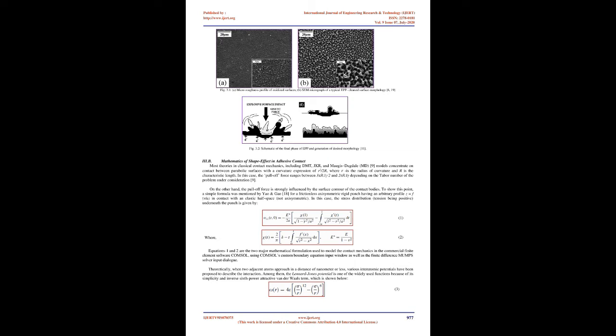2 general models of the contact behavior have been proposed: 1. The Derjaguin-Muller-Toporov, DMT, approach for small, stiff, and low surface energy systems, and 2. The Johnson-Kendall-Roberts, JKR [17], theory for large, soft, and high surface energy systems. The DMT model for sphere-on-flat contact predicts that the local contact stress transforms from compression to tension at the edge of contact area and attractive forces arise in the zone of molecular separation, just outside the contact area. In the JKR model, on the other hand, the attractive forces are assumed to act inside the contact area, and tensile stresses are again exerted close to the contact edge.